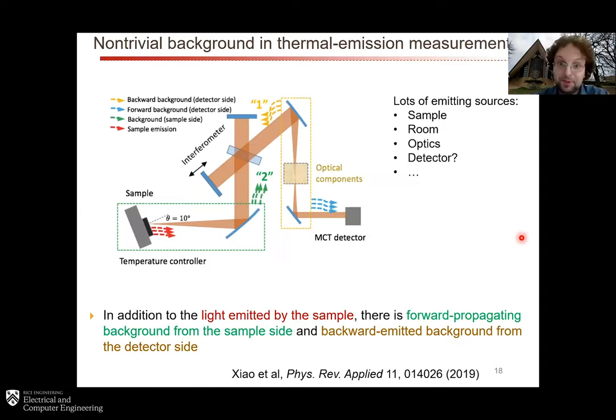So here's what we found out. Our system is a little bit more complex than just the sample and the spectrometer. In particular, we have the sample over here, and then after the interferometer, we also have a bunch of optical components. We have apertures and filters and things like that before this optical signal makes it all the way into the detector. And what we found out is that many things in this spectrometer were thermally emitting. So the beam splitter was a potential source of thermal radiation, the detector was a potential source of thermal radiation, but in particular, the biggest contributor, the one that it turned out was causing all of the problems, were the optical components between the interferometer and the detector that were emitting backward.